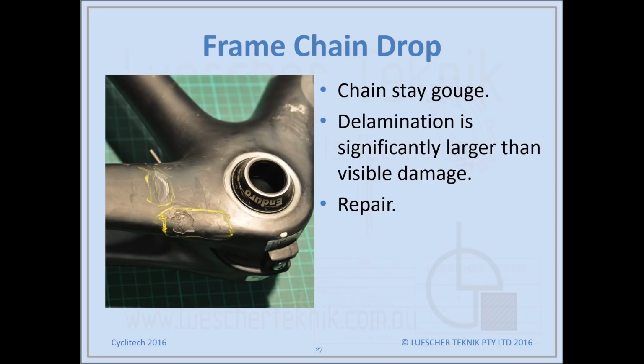Another common one is chain drop. With some frames, the clearance between the crank and the chainstay is such that when the chain gets wedged in there, it really creates a large delamination. In this case, there was a small visible gouge, but the area marked in yellow was delaminated. As you can see, it's quite a substantial area compared to what you can visually see.